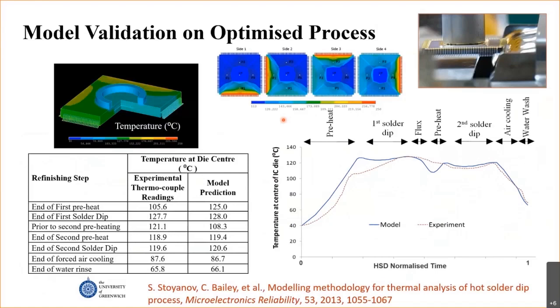These components were also thermocoupled at different locations to see how temperatures changed in the package as it's dipped in the solder bath on each side. And here we could see comparisons between the model and the experimental data. So here we have a real insight for a model that's been developed to understand how the temperatures change when we use different process conditions for this hot solder bath process.